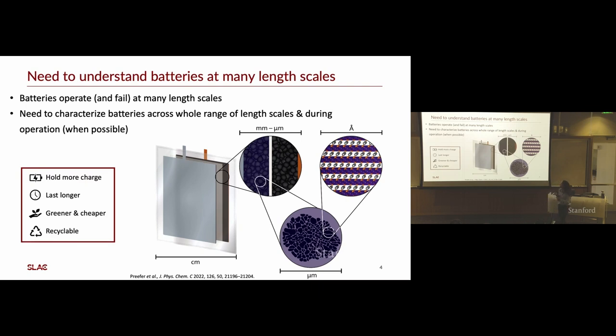So why do we characterize batteries, especially as they fail? Well, we want to know why they're failing, how they're failing, so we can make better batteries. And we need to characterize them across different length scales. So batteries typically are on a centimeter-sized scale. Their electrodes are 100 microns thick. You have an anode and a cathode. You have a separator in between that's filled with electrolyte. Each of those anodes and cathodes, those electrodes, are comprised of particles that are on the micron scale, but those particles are actually comprised of things that are on the angstrom scale.